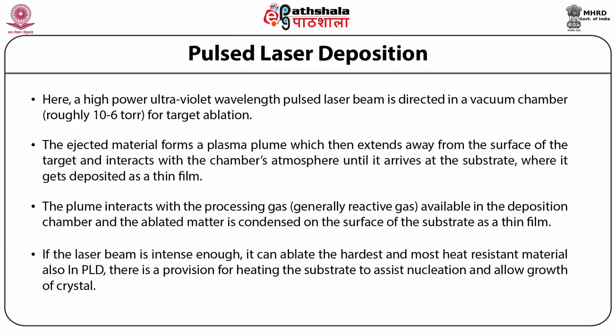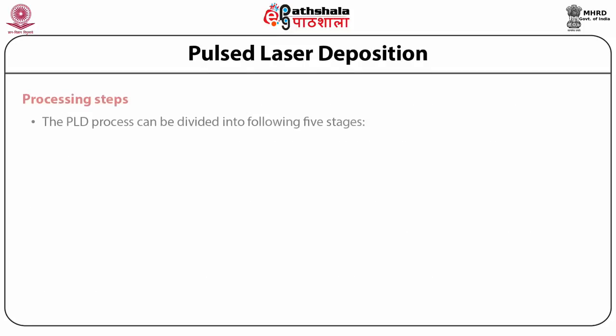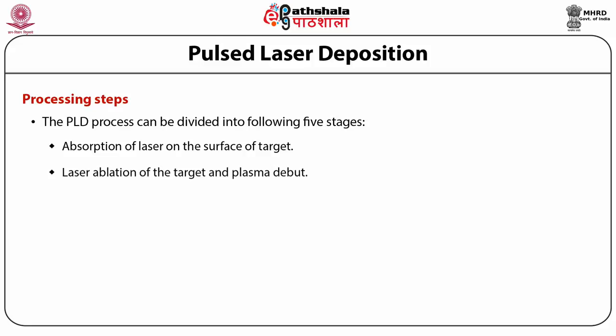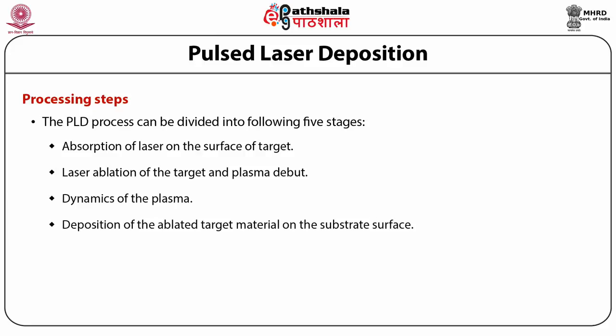In PLD, there is a provision for heating the substrate to assist nucleation and allow the growth of crystal. The processing steps of PLD are as follows. First, the absorption of laser on the surface of the target. Second, laser ablation of the target and plasma debut. Third, dynamics of the plasma. Fourth, deposition of the ablated target material on the surface of the substrate. Lastly, nucleation and growth of the film on the surface of the substrate.